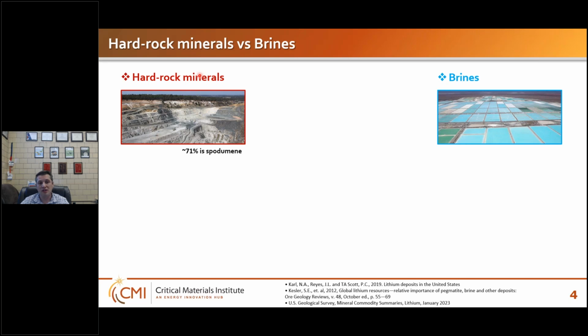Now, because of that, all industrial methods utilize a so-called decrepitation step, where they convert alpha spodumene, which is a stable, tightly packed structure, into beta spodumene, which is a more open structure and is more susceptible to chemical attack. The problem is this is being done at very high temperature. It is an energy intensive step and constitutes around 85% of the total energy cost of the process. The extraction is still done at quite harsh conditions, even though we convert it to a more susceptible structure.